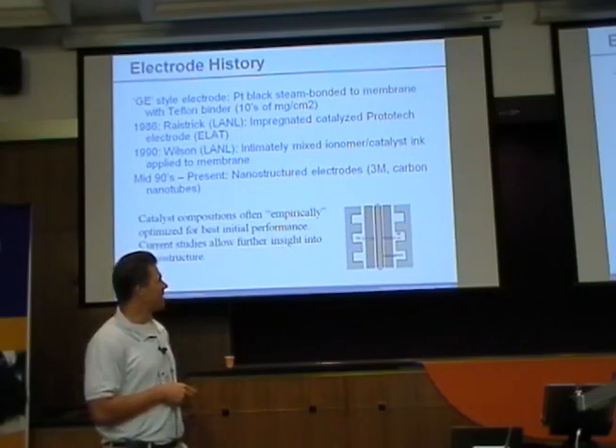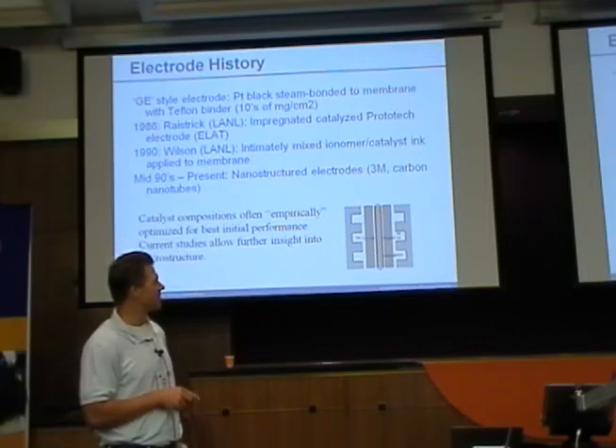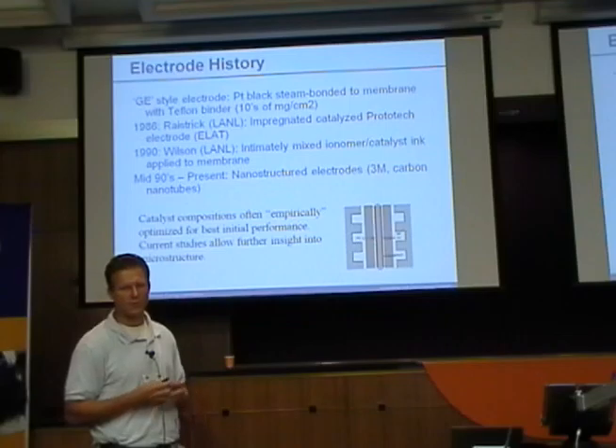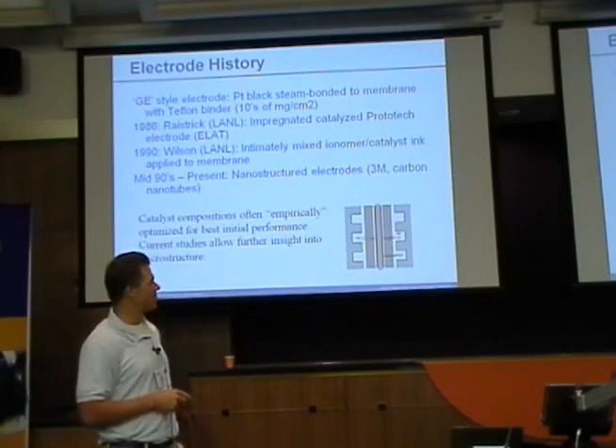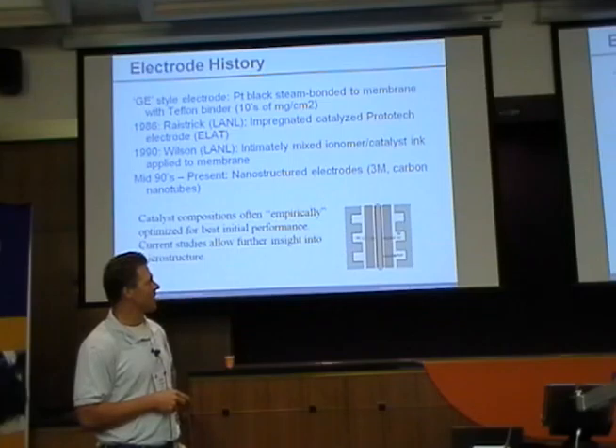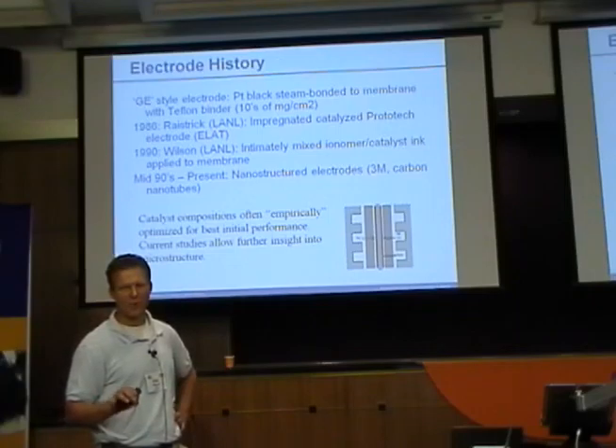And then in the late 80s and early 90s, two researchers, Mahlon Wilson, somebody who I interacted with quite a bit at Los Alamos while I was there, and Ian Raistrick, who was gone before I got there, basically came up with two major breakthroughs, which was dispersing the platinum on carbon and then integrating it with ionomer into electrode structures. And basically these tens of milligrams per square centimeter got reduced down to tenths of milligrams per square centimeter. And then all of a sudden, everybody got really excited about what you could do with these things